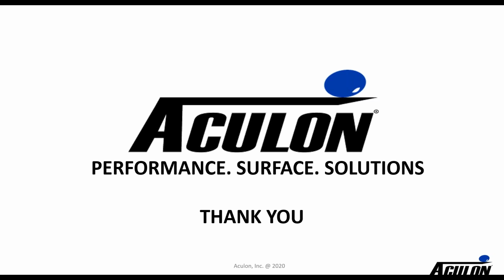Okay, do you have any plans to add color pigments to check the presence of nano coating on the surface? So this one's a challenge for us. We get this question because obviously some of our competitors have a gold kind of color in there. When you're at this kind of monolayer level, 2 to 4 nanometers, you don't have the ability to put a pigment in there. It would just sit on the top of the surface. It's when you go up to 2 to 4 microns that you can put a colorant in there, and you can see that. So we understand that's a bit of a challenge for some people. They prefer to be able to see it. So that's why we offer the dyne pen. It gives you the ability to test the coating's integrity. That's the option. Eventually we can figure out nano dyes that go into nano coatings. That would be something that we would certainly do.